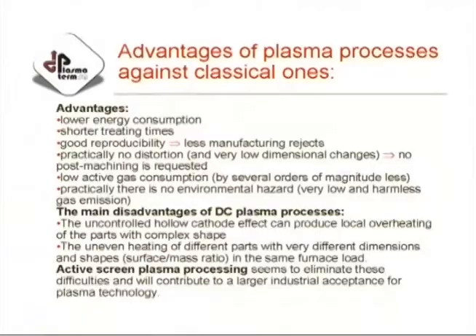First, we began to treat the parts not by plasma nitrocarburizing, but by gaseous nitrocarburizing, low temperature nitrocarburizing. Well, certainly then later we shifted to plasma, because plasma has a lot of advantages. First of all, a low energy consumption, shorter treating times, a very good reproducibility of the results, so less manufacturing reject and cost. Then practically no distortion appears due to the low treating temperature, and a very low active gas consumption.